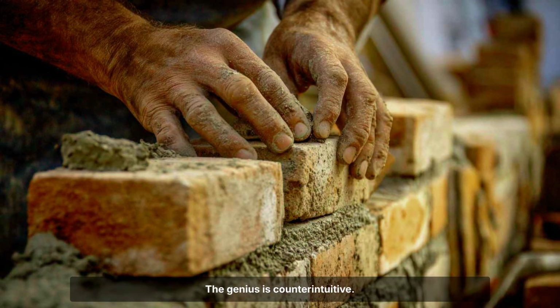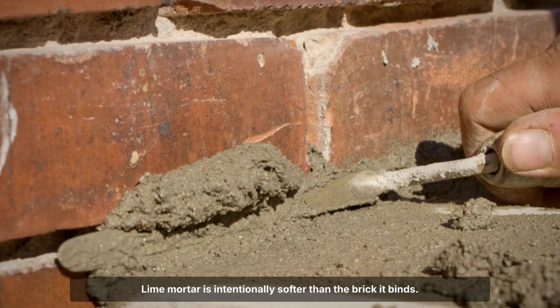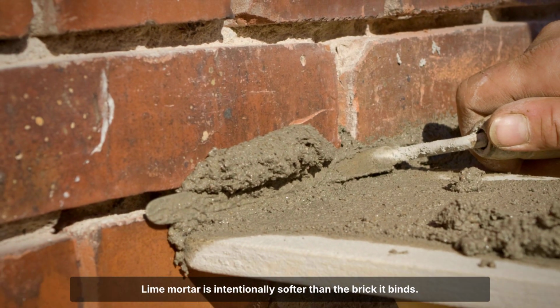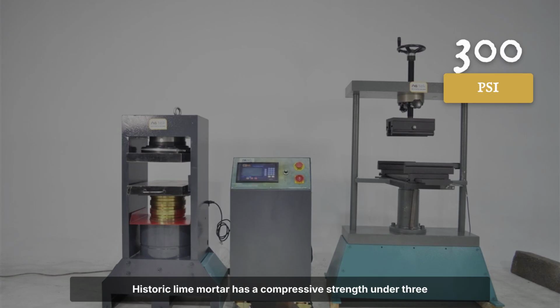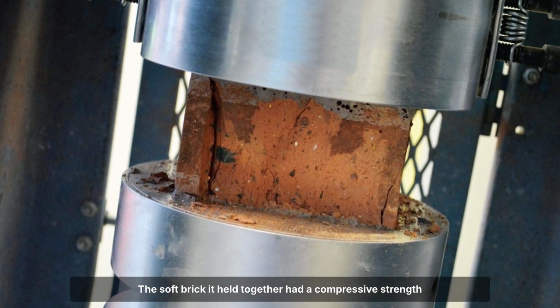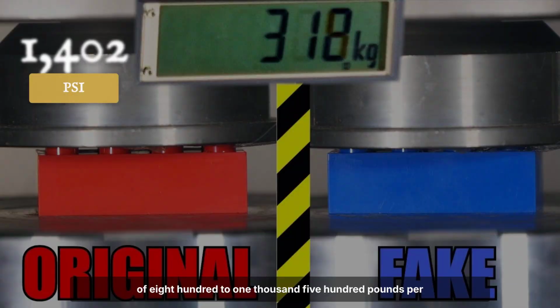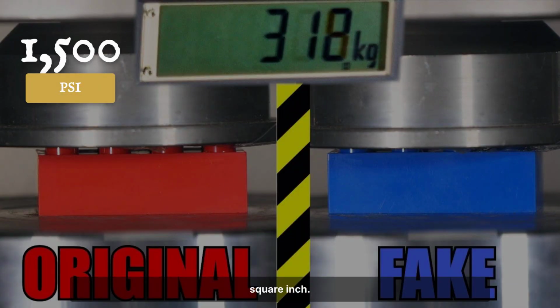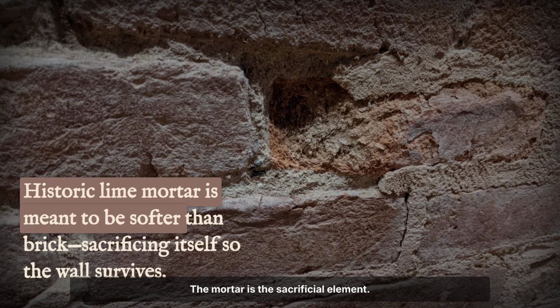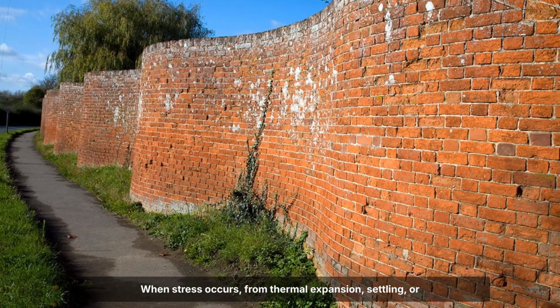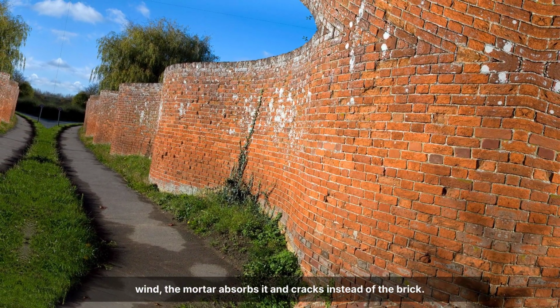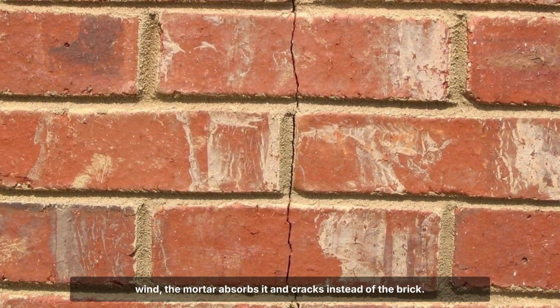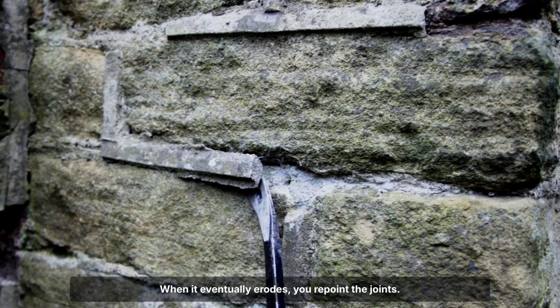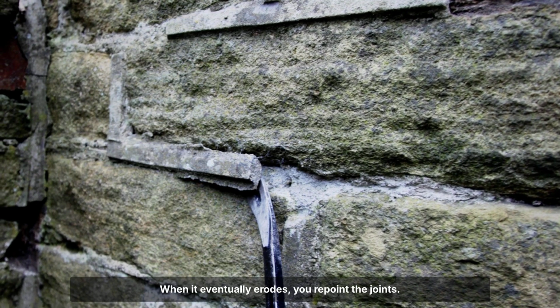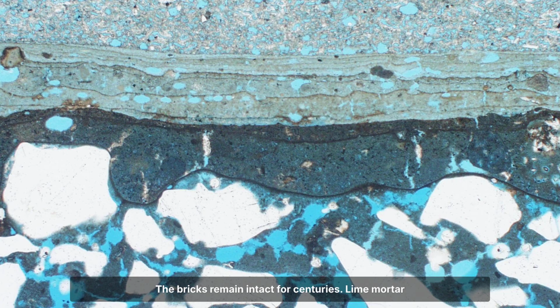The genius is counterintuitive. Lime mortar is intentionally softer than the brick it binds. Historic lime mortar has a compressive strength under 300 pounds per square inch. The soft brick it held together had a compressive strength of 800 to 1,500 pounds per square inch. The mortar is the sacrificial element. When stress occurs from thermal expansion, settling, or wind, the mortar absorbs it and cracks instead of the brick. When it eventually erodes, you repoint the joints. The bricks remain intact for centuries.